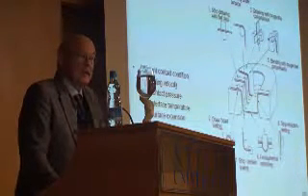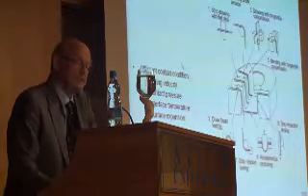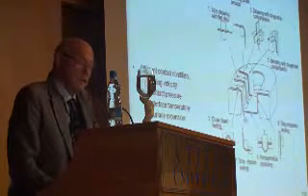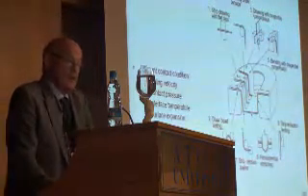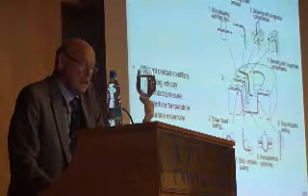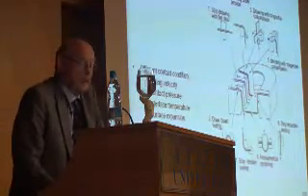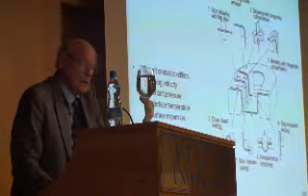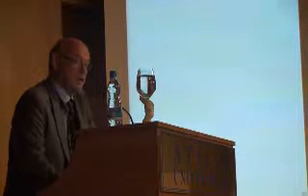Sheet metal forming is many things, and the number of simulative tests to model sheet metal forming are plentiful. This is a schematic drawing of a deep drawing, where you may model the conditions in the flange. We haven't shown the blank over here, by strip drawing between flat dies. You may have drawbeads, which can be modeled by drawbead testing. You will have bending under tension in the die radius of curvature, and you may have ironing after the deep drawing operation. So, several tests are required for testing the lubricants since the conditions are so varied.